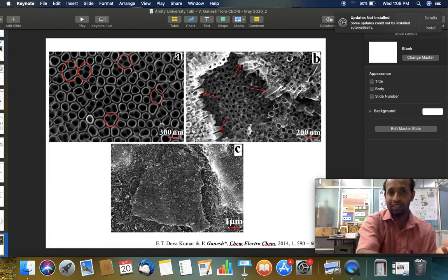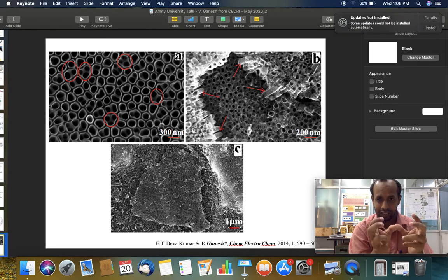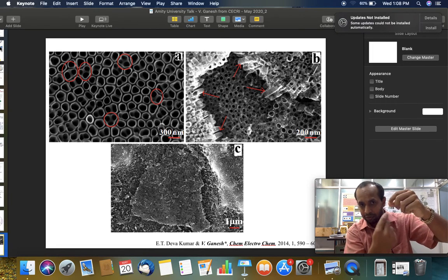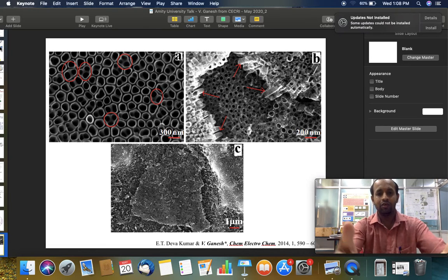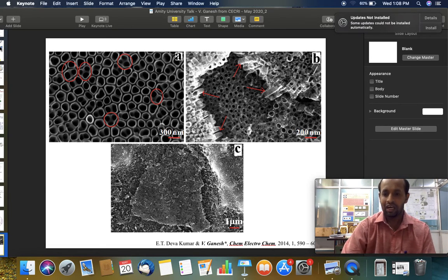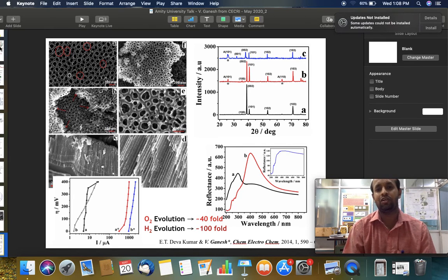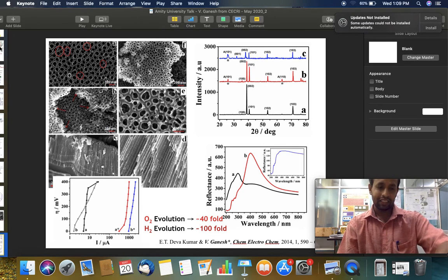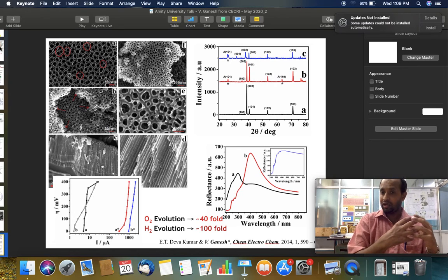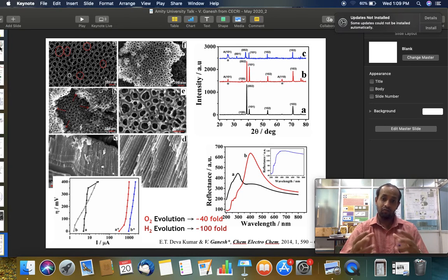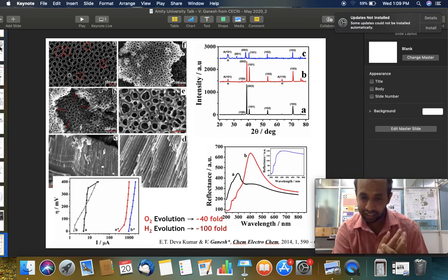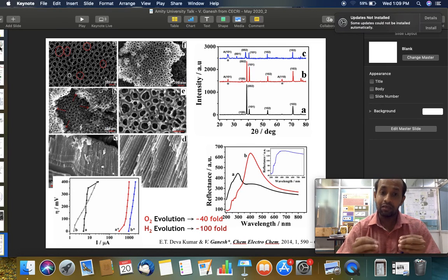So as you can see, you have in some areas clumped nanotubes, and you can alter the length and the ripples along the nanotube. Essentially, you can even come up with a honeycomb-based structure, and that could be used as an efficient electrocatalyst for the water splitting reaction. From the careful plot analysis, one can see that compared to the non-anodized one, just a bare substrate, oxygen evolution is enhanced roughly 40-fold in the oxygen evolution reaction, and a similar 100-fold enhancement in the rate constant associated with hydrogen evolution is observed, which is very good, right?